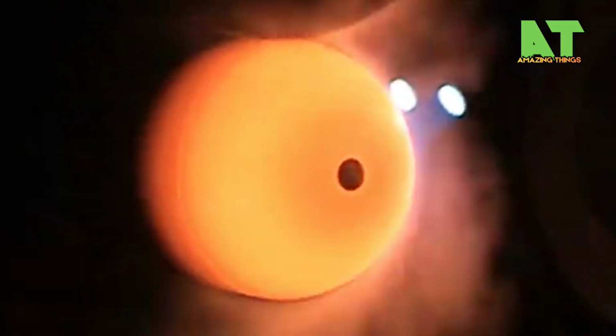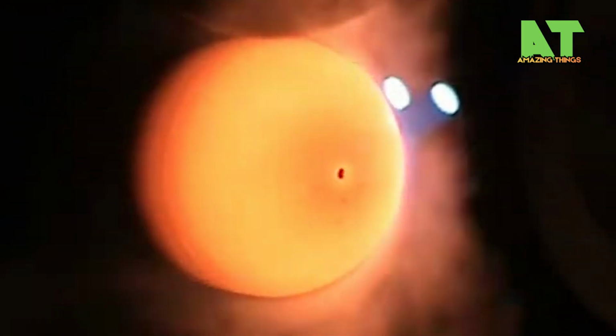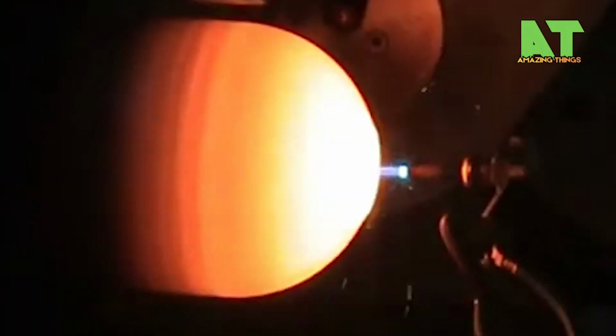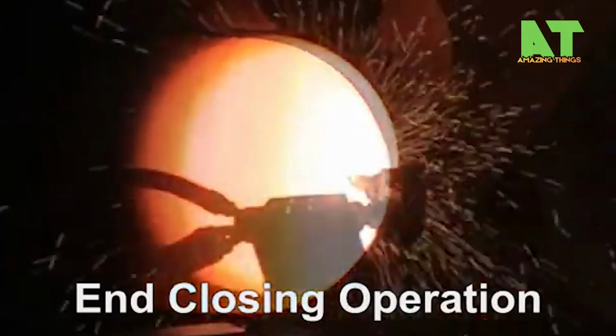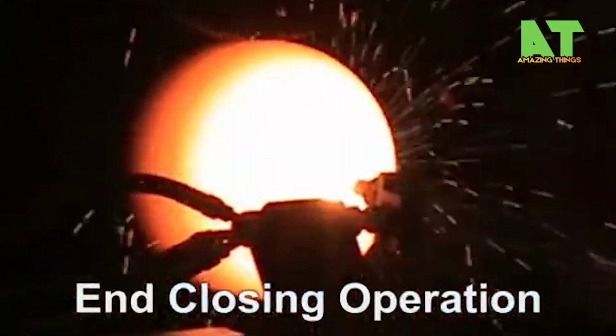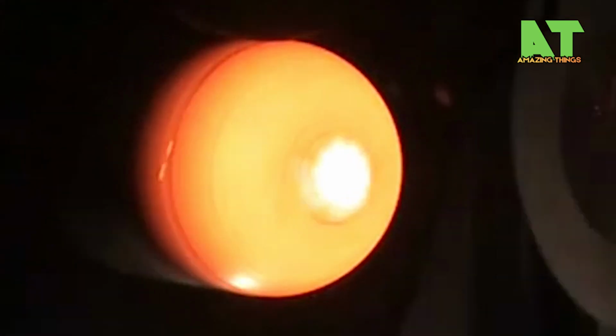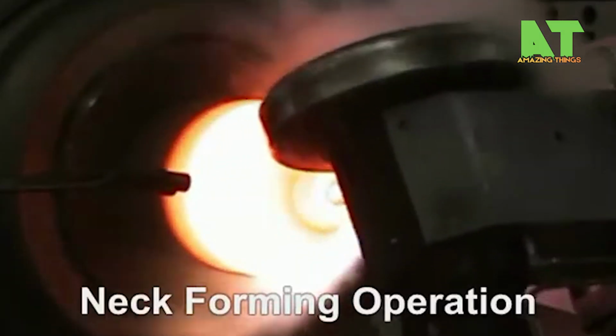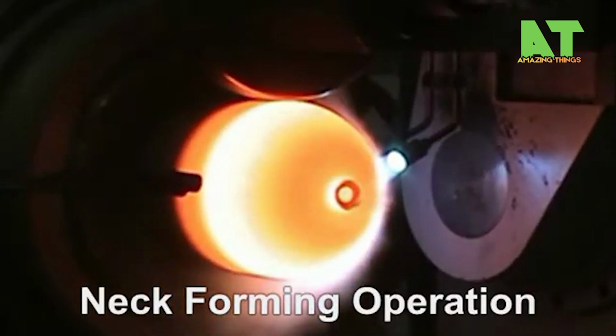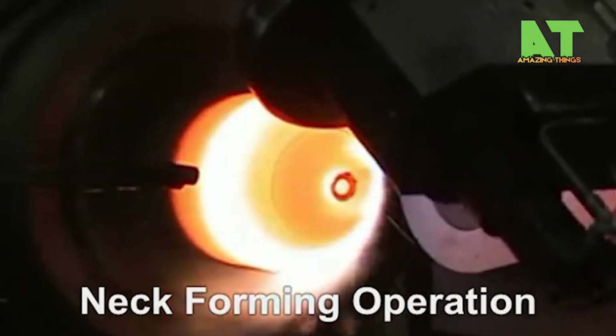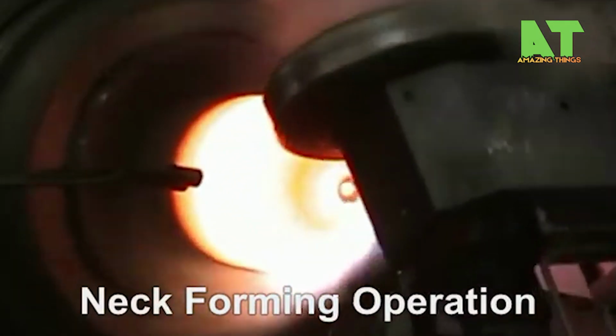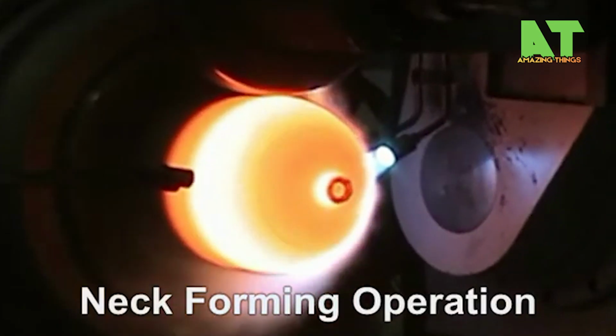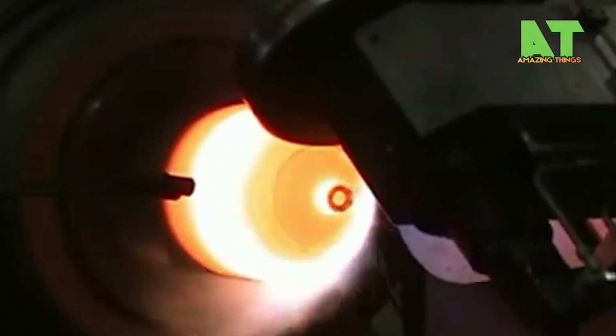The tube is loaded into the machine and rotated at high speed while powerful induction heaters bring the end sections to forming temperature, typically between 900 degrees Celsius and 1,000 degrees Celsius. At that temperature, the steel becomes plastic and workable. A set of precision-forming rollers then applies controlled radial pressure, thinning and elongating the tube wall to achieve the exact wall thickness and diameter required for the cylinder body.